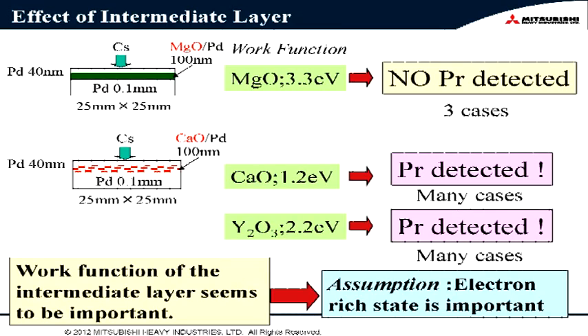Okay. And the next point is the effect of the intermediate layer. Usually we use calcium oxide. If we use magnesium oxide instead of calcium oxide, we tried 3 times, but we detected no praseodymium. But if we use Y2O3, we detected praseodymium many times.